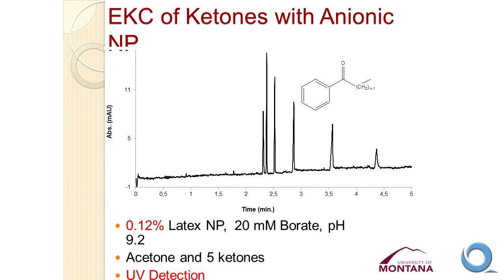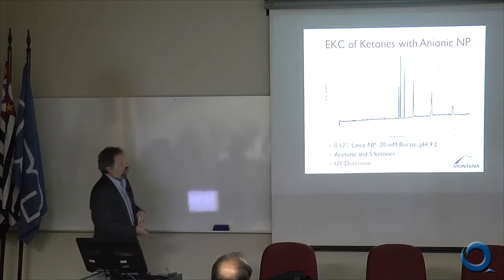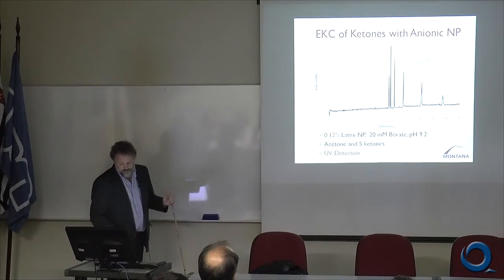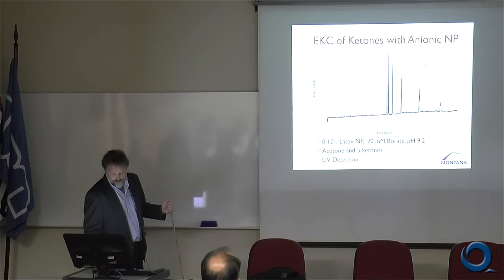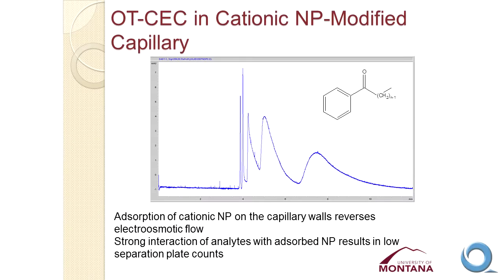Just a quick step away from that, we had already demonstrated that with anionic nanoparticles, we could achieve very nice separations using nanoparticle materials in electrokinetic chromatography. But as soon as we put these cationic nanoparticles into the system, we started to get separations that looked like this. And this is, of course, not at all what we wanted.